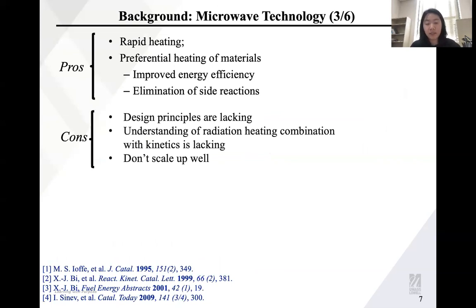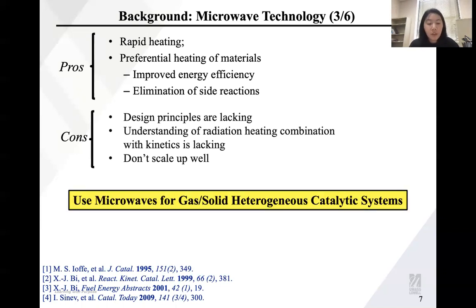Using microwaves has its own advantages, such as rapid heating and preferential heating of the material, which can improve the energy efficiency. If you apply microwave heating to a highly microwave-absorbing material, it can heat rapidly and improve the energy efficiency. At the same time, in gas-solid reactions, your solids can be preferentially heated by the microwave, while your gas phase stays cold because it can't absorb microwaves, which eliminates side reactions in the gas phase. So we want to use this advantage of microwave technology for gas-solid heterogeneous catalytic systems.